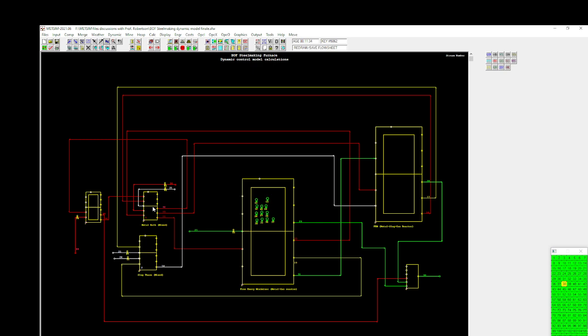So basically all these reactors are defined appropriately in accordance with the various stream properties which are coming in and which are going out. Accordingly, we have defined three free energy minimization reactors, starting from the metal gas reactor that defines the hot spot zone, a metal gas slag reactor which defines the immersion zone, and a metal gas reactor which defines the entire bath. This has been defined to include the effect of argon purging in the last 30% of the process.